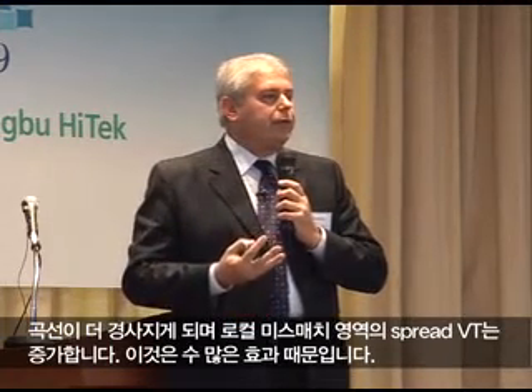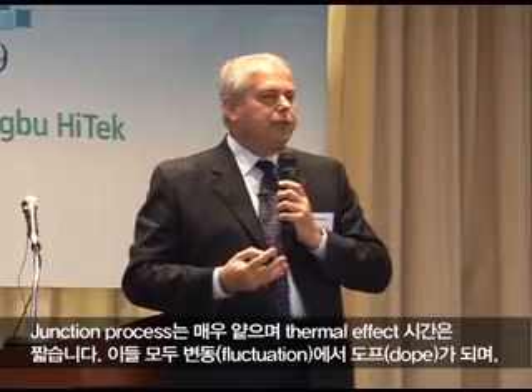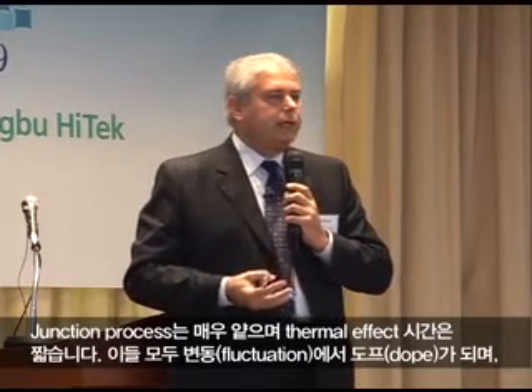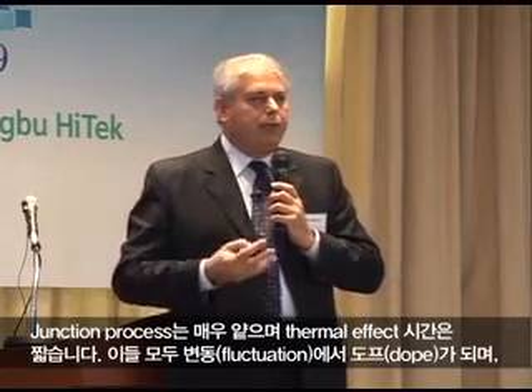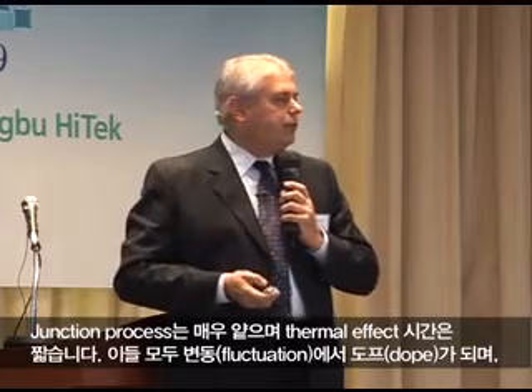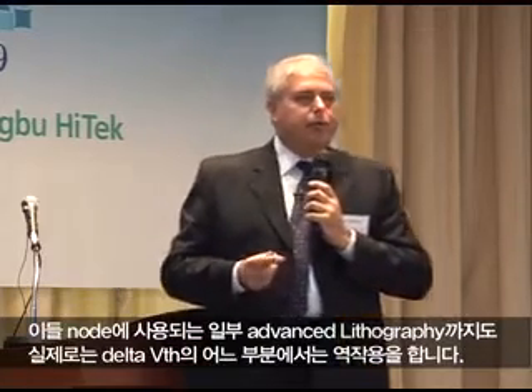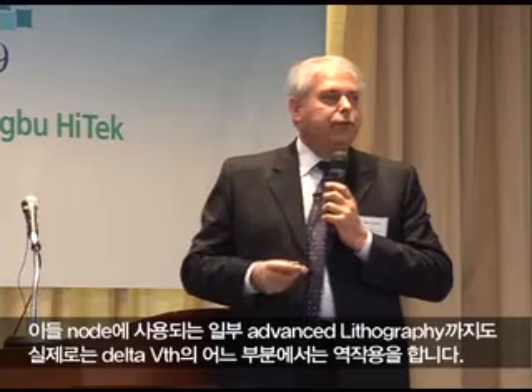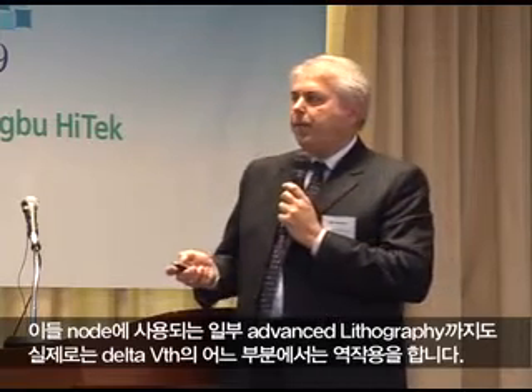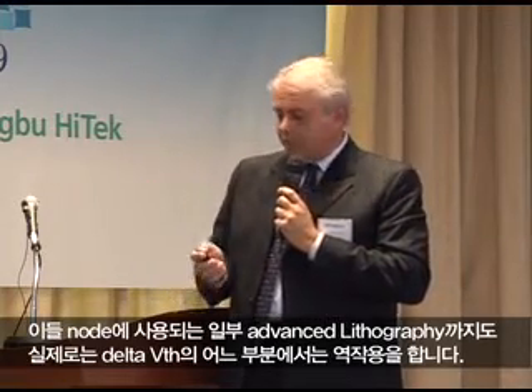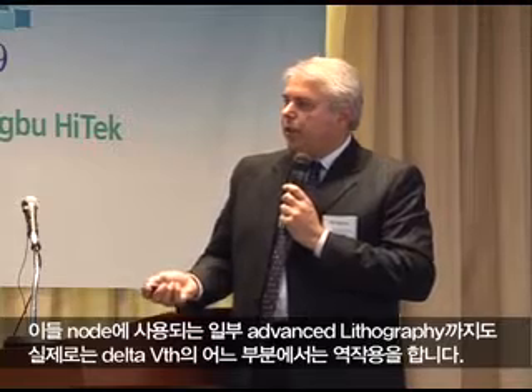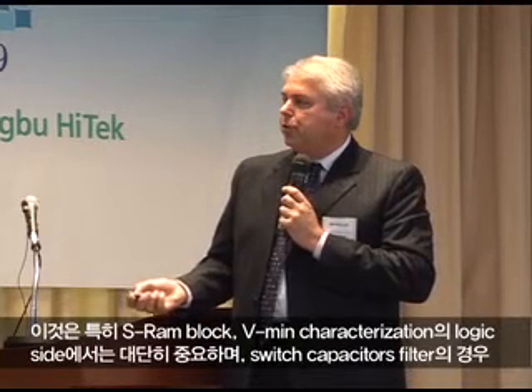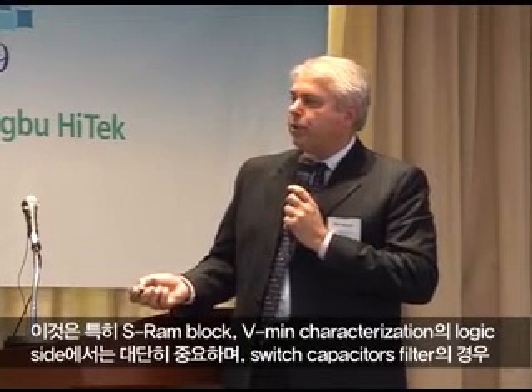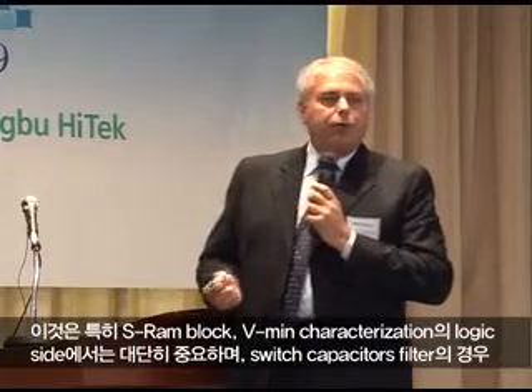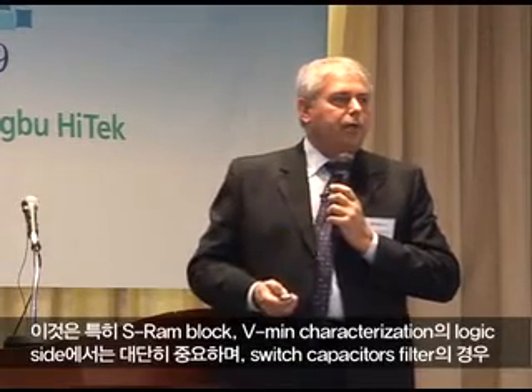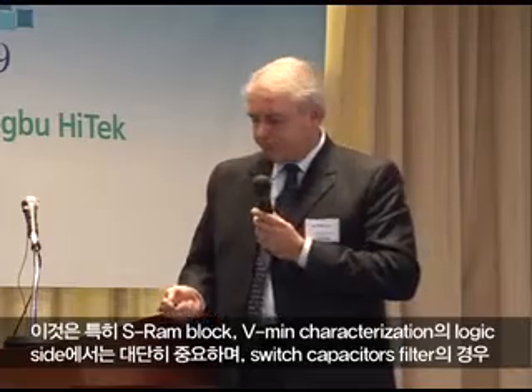This is due to a number of effects. There's a very shallow junction process, very short time thermal effects, and they all lead to dopant fluctuations, and even some of the advanced lithography that's used for these nodes actually works against you in some of the delta VTH. This is especially true, or this was first very important in the logic side for the SRAM block V-min characterizations.